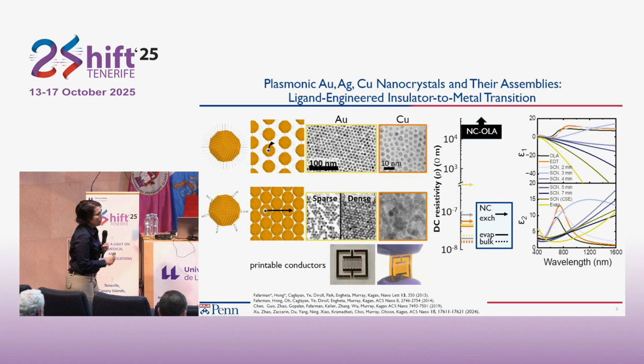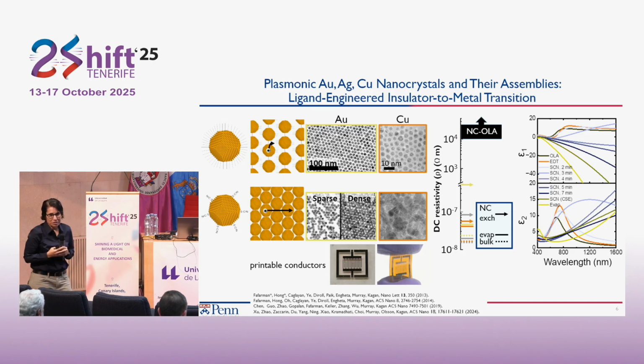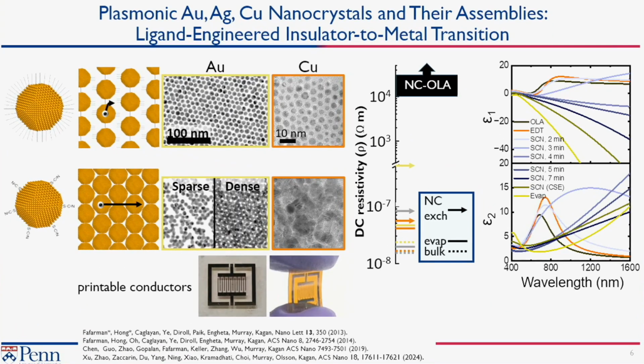Okay. So what's different about nanocrystals? I'm going to start with metals. It's an easy way to understand the characteristics. We can make metal nanocrystals. We've done the same thing with gold, silver, and copper. I'm showing 2 out of the 3 here. If you take gold nanocrystals as they're synthesized, in these examples, they have organic ligands on the surface. You can look at an electron micrograph and see the inorganic cores, and all the white space is, in fact, the organic ligands that separate them.